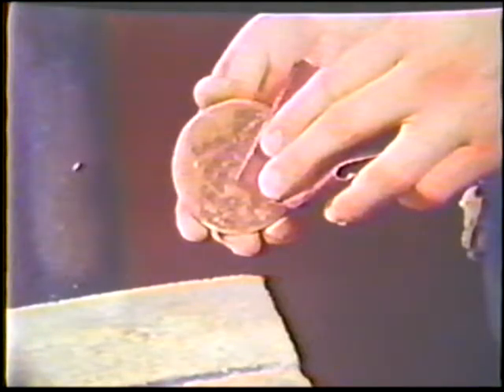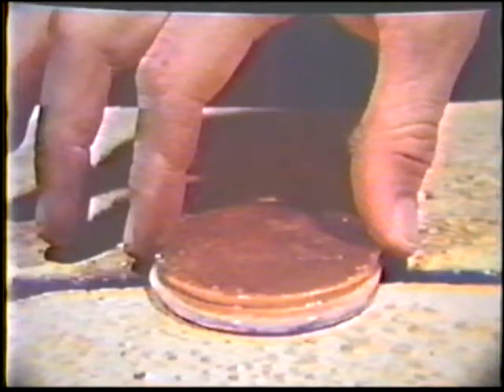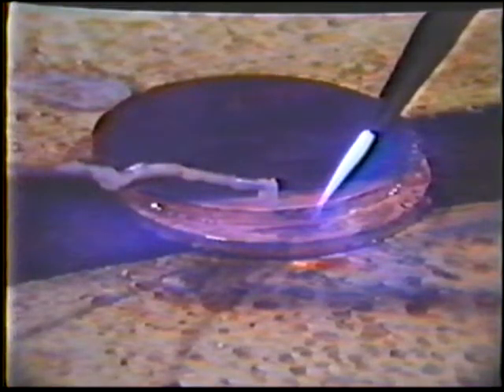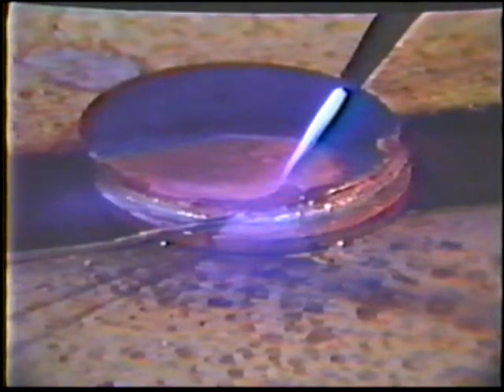The process consists of cleaning the mating surfaces of the joints, coating them with flux, placing them tightly together, heating the joint area to the melting point of the filler metal, and adding the filler to the edge of the joint, allowing capillary attraction to draw the metal into the joint. Watching the behavior of the flux is the best way to determine when to add the filler metal. The flux first dries out as the moisture boils out. Then the flux turns a milky color and starts to bubble. And finally, it turns into a clear liquid at about 1100 degrees Fahrenheit. This clear appearance is the indication that the filler metal can be added.